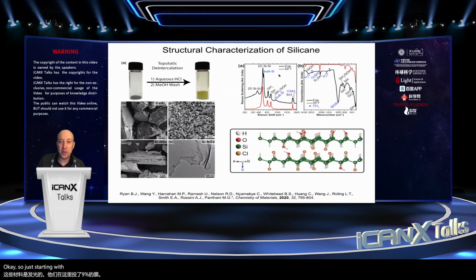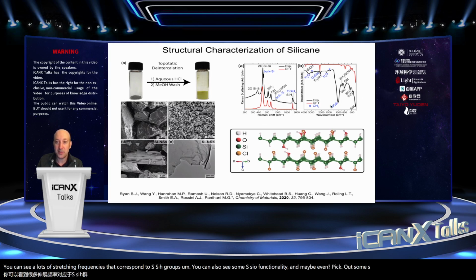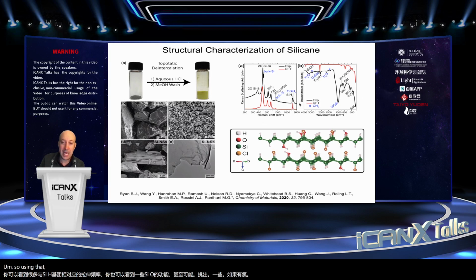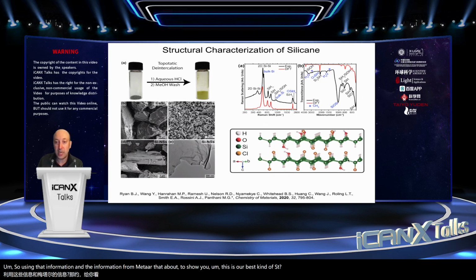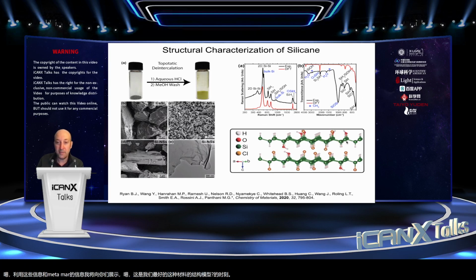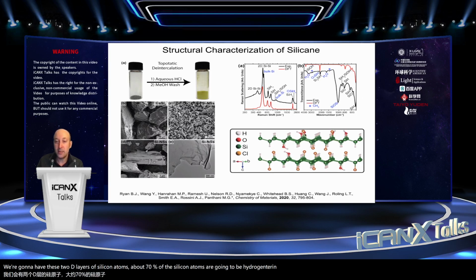Okay, so just starting with Raman and FTIR spectroscopy, this was work that Matt's group did. You can establish some of the functional groups that should be present. You can see lots of stretching frequencies that correspond to Si-H groups. You can also see some Si-O functionality and maybe even pick out some Si-Cl. So using that information and the information from NMR that I'm about to show you, this is our best kind of structural model for this material at the moment. We're going to have these 2D layers of silicon atoms. About 70% of the silicon atoms are going to be hydrogen terminated, 20% are going to be chlorine terminated, and about 10% are going to be hydroxyl terminated.